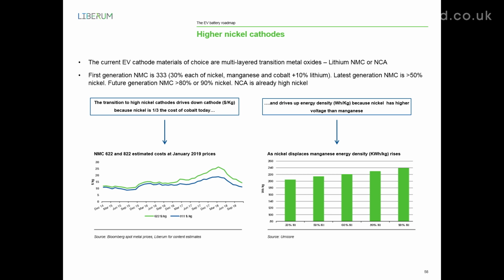These materials, which omit the word lithium, are lithium based, in the first stage lithium carbonate based, and they typically have 10% lithium and then a mixture of those other metals, nickel, manganese, cobalt, or instead of manganese, aluminium. And first generation was 333, an equal mixture of those metals. And the transition sees us going to 811 NMC. NCA, which is used by Tesla, is already at the 811 level. It's already 80% nickel. And the other car makers are adopting NCA batteries, which will transition to that level.